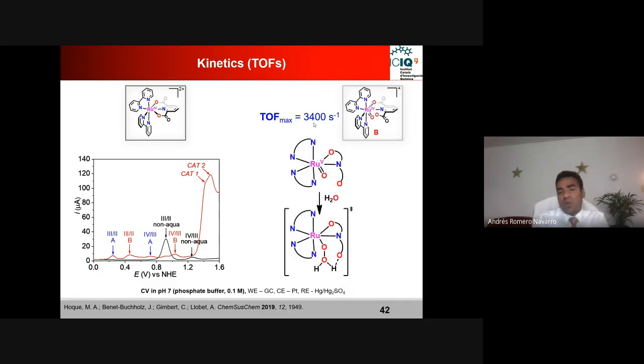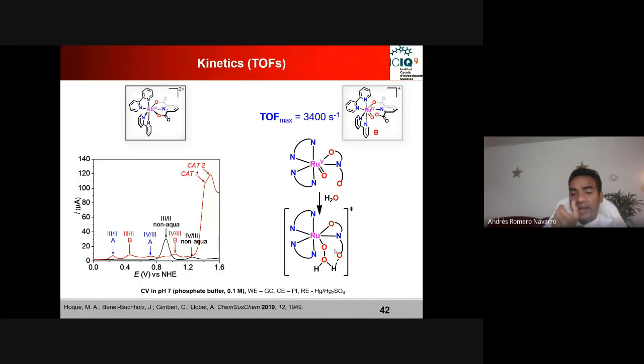And then we thought, okay, why is this showing such a good activity? And then we found that once we have, so here I'm showing just the schematic, the coordination sphere of that molecule. So let's say here I have this ruthenium-5 oxo compound, and one of the carboxylates is dangling. So when it is dangling, it is doing this hydrogen bonding interaction with this water molecule. Due to this hydrogen bonding interaction, the water molecule is coming closer to that carboxylate, and ultimately it is coming closer to this metal oxo group. And when it is coming closer, it will form this water nucleophilic attack, and that helps to form this oxygen-oxygen bond. And that was the reason it was showing such a high turnover frequency.